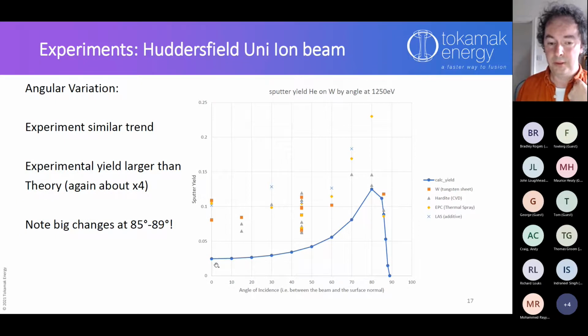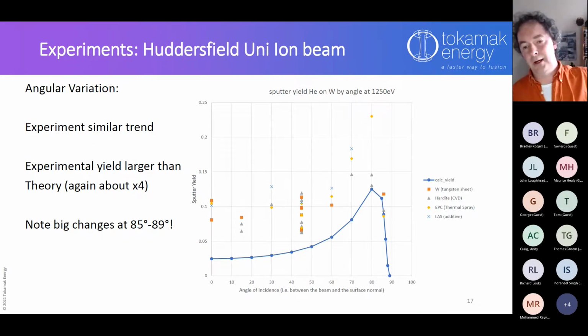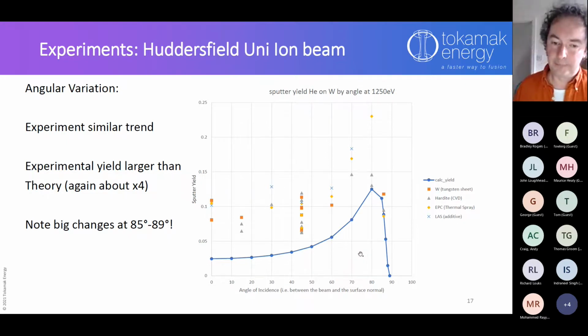The code also gives us angular distribution, so the blue line is my code predictions. At different angles, you get different sputter yields. It rises up and rises up until you get a very grazing incidence, and then it rises down. Of course, at 90 degrees, it's 0 because any beam of plasma or ions just flies past and isn't going to hit. Again, the squares, the triangles, and whatnot are different samples being eroded at different angles.